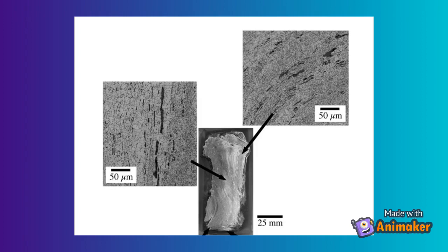This figure shows the microstructure of one of the rivets from the Titanic. The rivets were wrought iron composed of iron silicate slag. An analysis of a rivet found it was composed of over 9% of the slag. This is over 3 times the expected amount and greatly impacted the strength of the material.